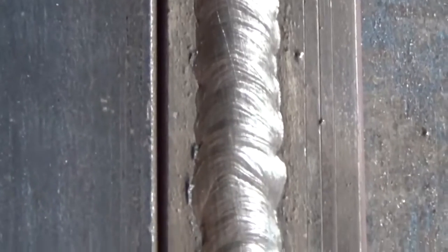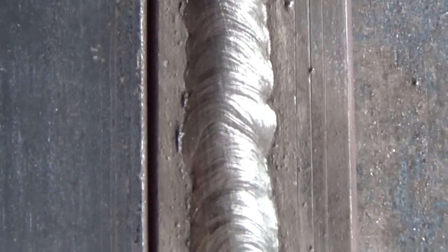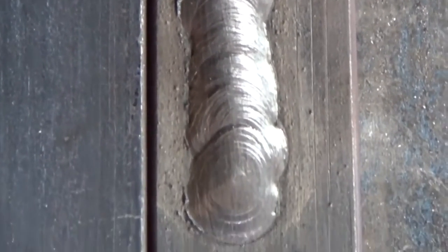Rutile coated electrode, negative, the current is 78 amperes. Please note that the liquid metal spreads better on the details. Welding is faster. The arc is more stable, with more penetration. It is necessary to clean off the slag and inspect the weld. The weld has a flat top, wider than in the first case. Poor fusion is not visible. In principle, the current is appropriate, but I would add 5-7 amperes.